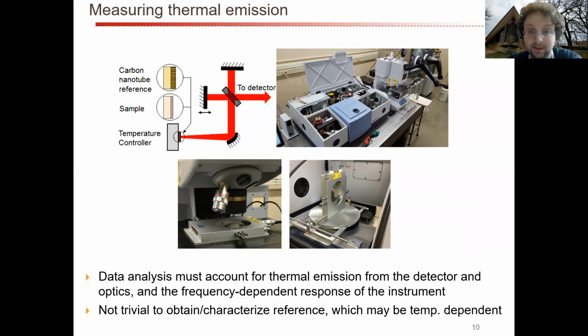So your data analysis after you've done the experiment has to account for thermal emission from the detector, from the optics. It has to account for frequency-dependent response of the instrument, so kind of the responsivity of the detector, the transmission of the optics. It's not necessarily trivial to obtain and characterize a really good standard reference, which also may be dependent on temperature, and so that becomes a problem. So this is actually rather difficult to do.